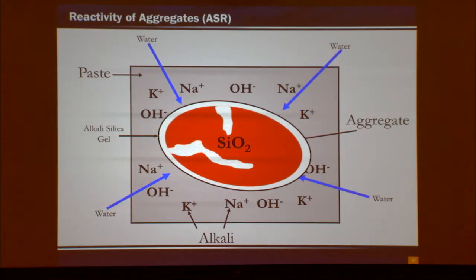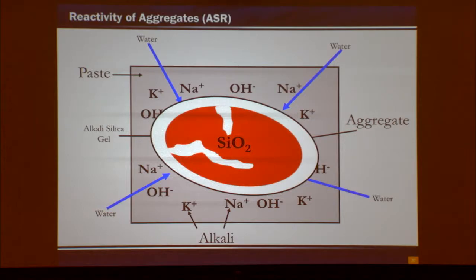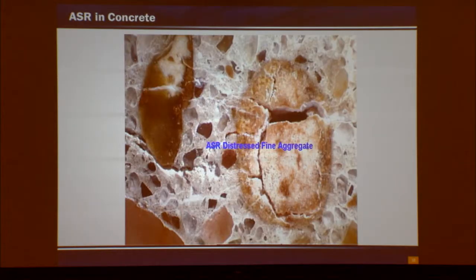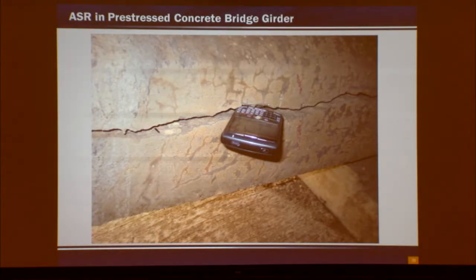Okay, no biggie. We got gel. You see ASR in probably everyday concrete. The problem is if that gel is expansive, it will grow, exert pressure, and then ultimately crack the concrete. So again, trying to avoid cracking the concrete is the main goal of any durability aspect. So does this really happen? Yes. Here are some aggregates from Texas concrete that has severe deterioration, a lot of ASR gel going on. Here's a prestressed girder. It's okay, no blackberries were harmed in the making of this photo. But if you're ever wondering what happened to all our blackberries, we fill cracks with them.